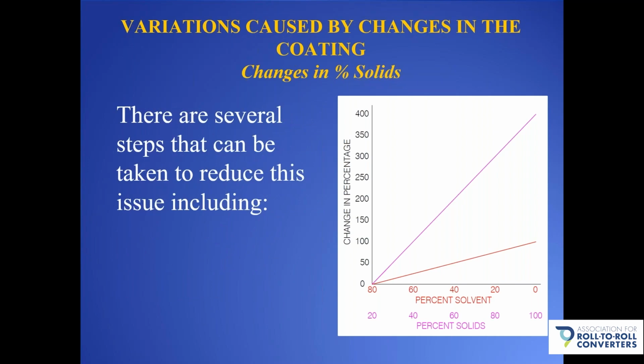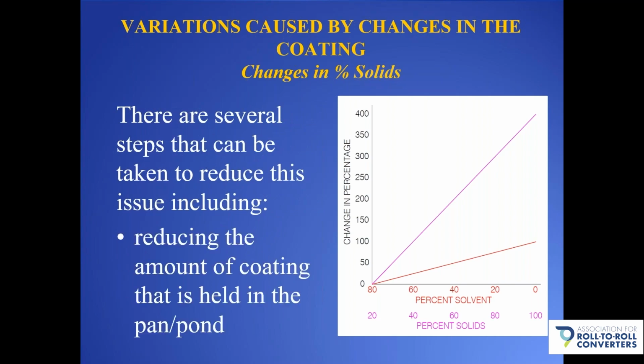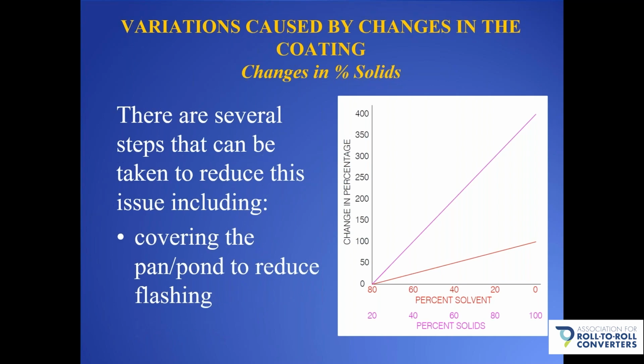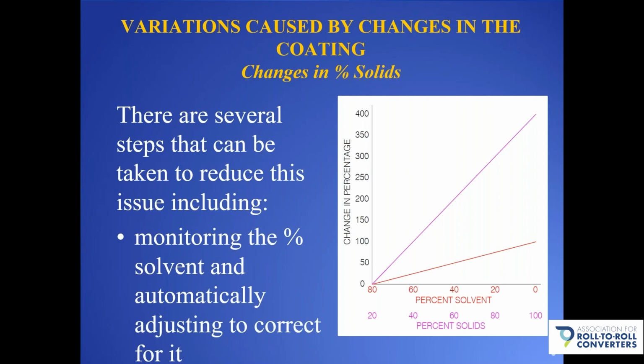Now, what can we do to address this issue? Well, a couple of things. First of all, the easiest way is to reduce the amount of coating that's held in the pan or pond, giving it less time to be exposed and therefore less time for solvent evaporation. Cover the pan or pond to reduce the evaporation or flashing. Or monitor the percent solvents and automatically adjust to correct for it. And there are systems that you can use that automatically do this, sample the solvent, and then continuously replenish it.